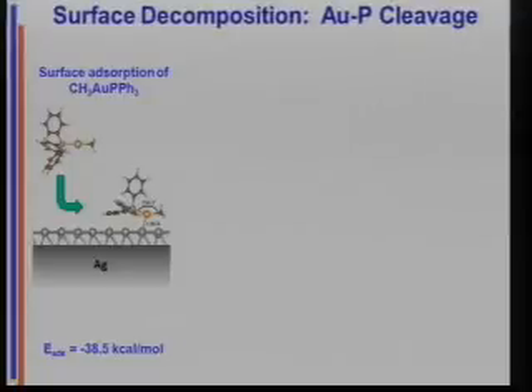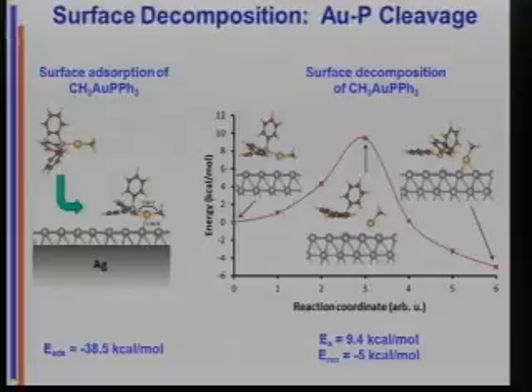Okay, so what's going on? Well, we decided to look at this computationally. This is a collaboration with Charles Musgrave at Colorado. And the first obvious thing is, well, the precursor adsorbs onto the surface and decomposes. So here, computationally, is adsorption of the precursor onto the surface. It's about 38 kcals downhill. And so then you calculate that you lose the phosphine, okay, you end up with gold methyl, there it is, okay. This all looks like reasonable activation energies.